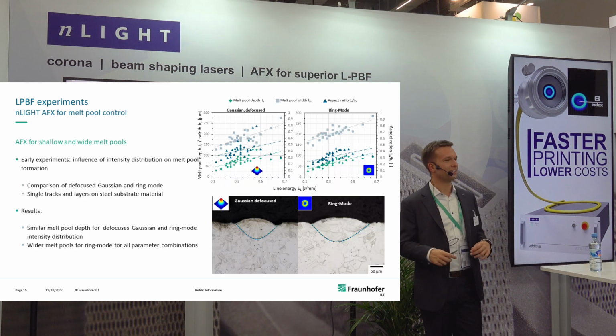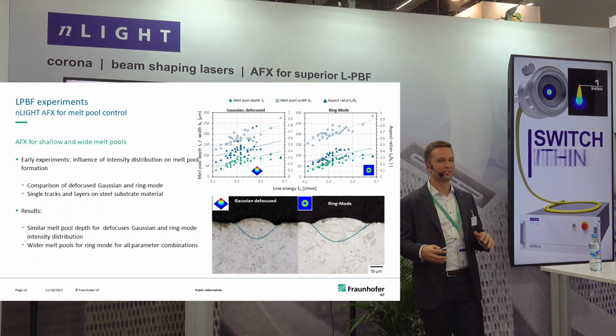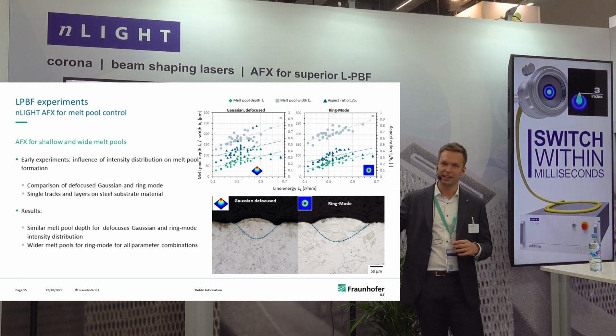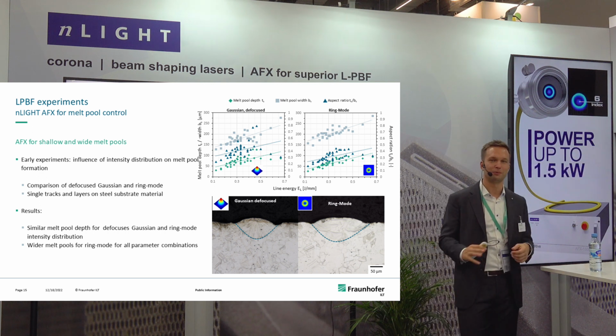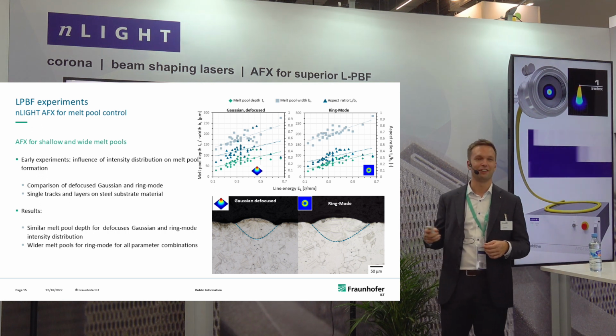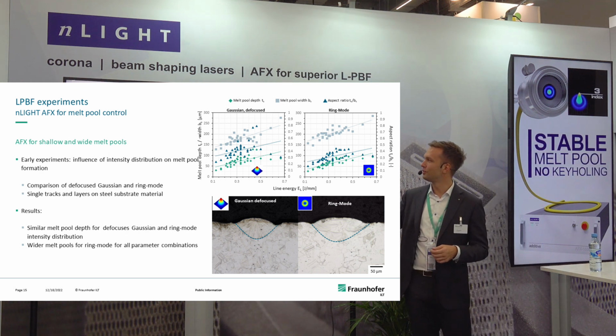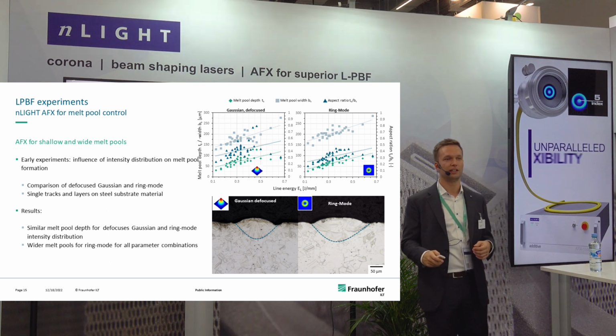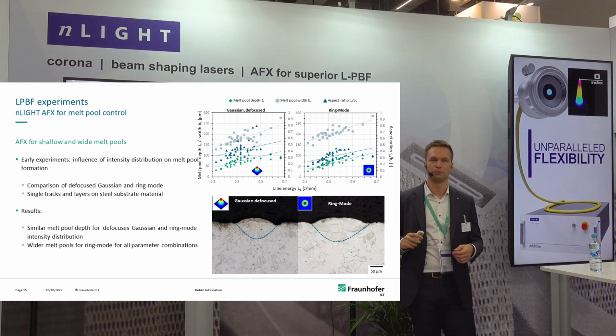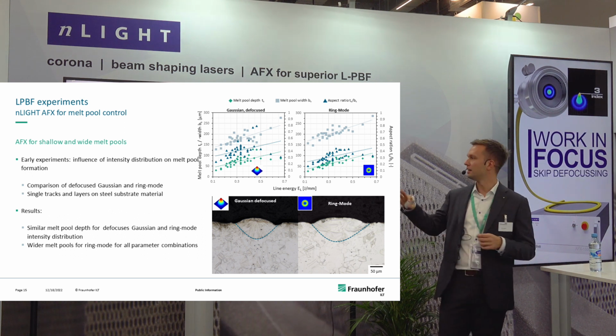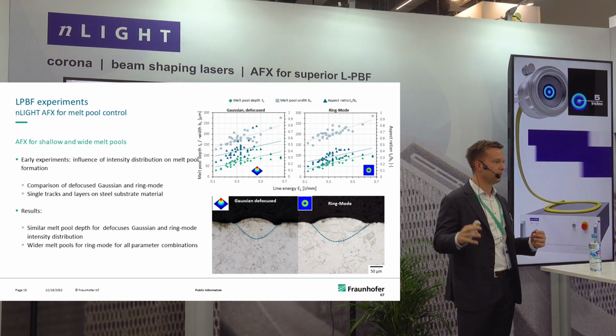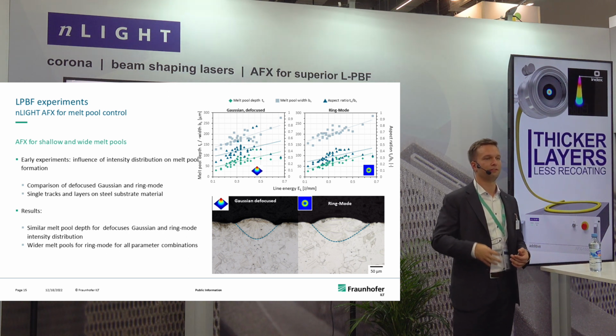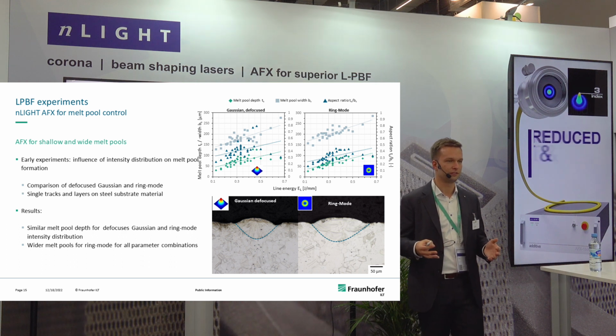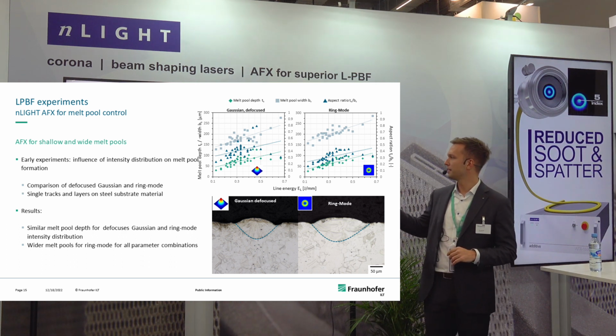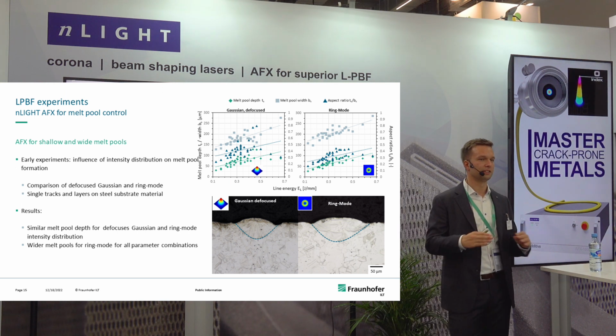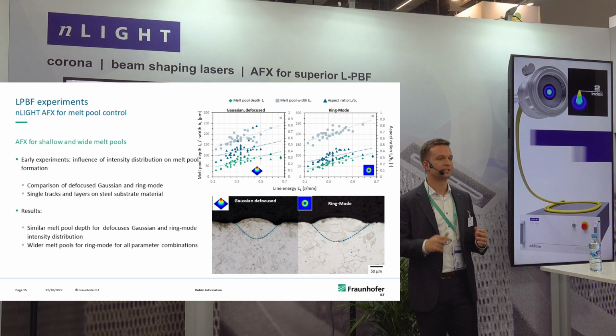So we figured out it would be very useful to do some additional tests based on the results we already had from the AFX. We already knew that we can generate very nice and flat melt pools with it. When you look at the graphs, even compared to the defocused Gaussian beam of similar diameter, you end up with a much wider melt pool of similar depth, which gives us enough leeway to have robust processing and not end up with a lot of defects due to lack of fusion, but sufficient width, and the width to depth ratio is quite small.